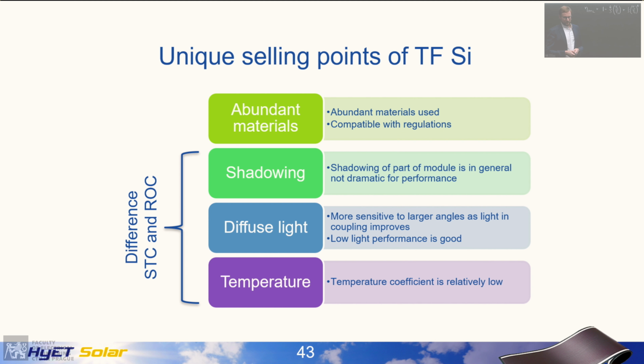There are some unique selling points. First of all, in thin film silicon, we use only abundant materials. And it is possible to have only very limited performance losses due to heating. So this temperature coefficient, which is apparently also quite low for perovskite, I didn't know that, but for amorphous silicon it is also much lower than it is for crystalline silicon. That's one of the good things about it.